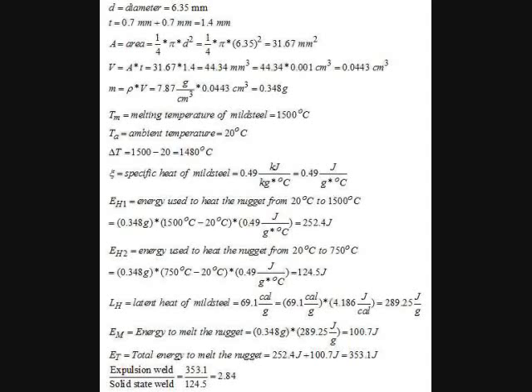Another point which is very important is this 124.5 joules. To make a good weld, all the 0.7 plus 0.7, I normally need around 1200 joules of energy, which is 10 times this 0 to 750 degrees C number. So I can estimate how much energy if I weld a nugget by using the 124.5 multiplied by 10.